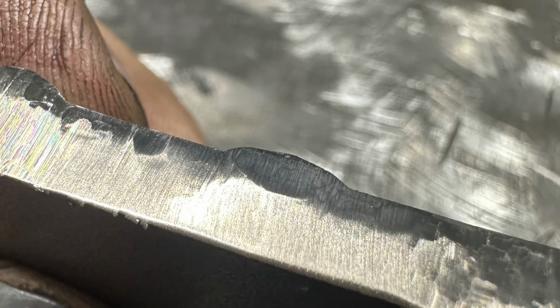Now, I don't think this is hydrogen embrittlement cracking. What we have here is what happens when you run an alloy too hot into a base material and the alloy is really hard, abrasion resistant. Well, what ended up happening is it mixed too much with that base steel, and when it cooled, it just basically couldn't handle it and cracked off.